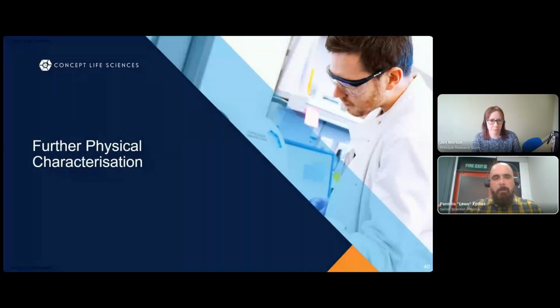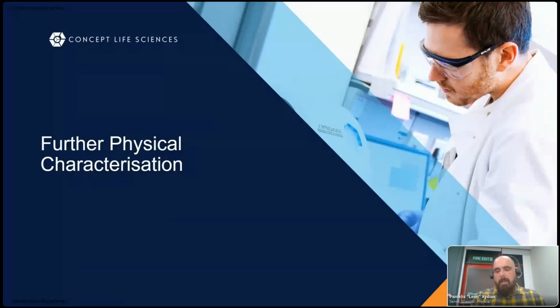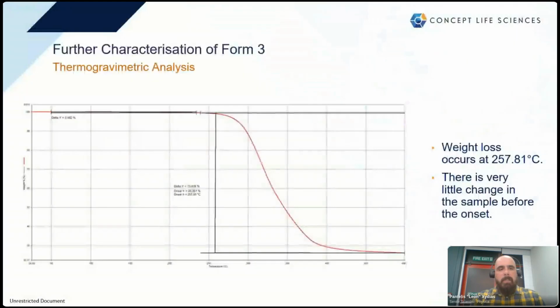So hi again, thank you, Jen. So as Jen said, we got form 3. We had a lot of it, and it was a good time for us to benchmark these form's properties. We ran some basic characterization with the TGA. Nothing very exciting. There is one step, at approximately 257 degrees Celsius, as we can see from the thermogram. This is very typical. You have the decomposition of the material.